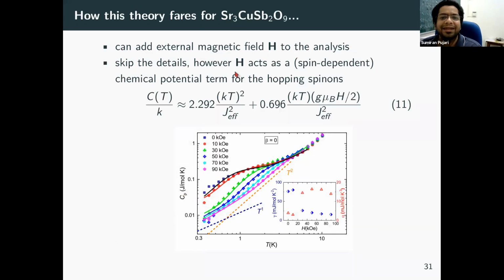We can also add an external magnetic field to the analysis, and do all of the mean field analysis, and you get a T squared component, and you also get a linear in T component when there is a non-zero external magnetic field. So this is the prediction of this Dirac spin liquid ansatz-based mean field theory. And it turns out this happened to explain the data quite well.